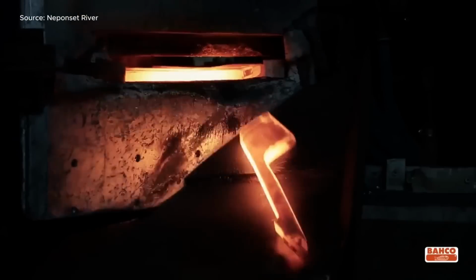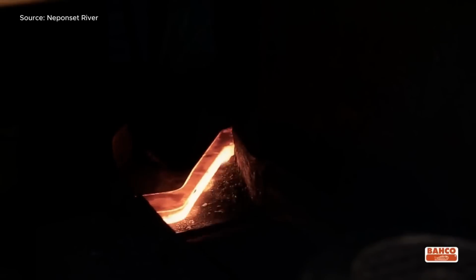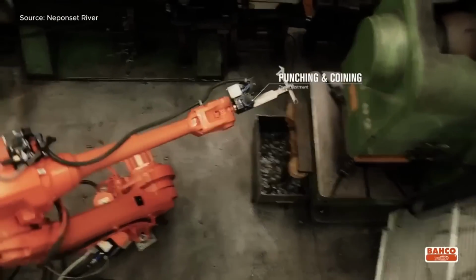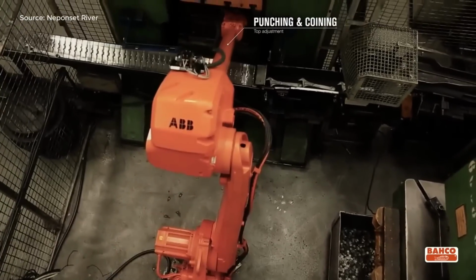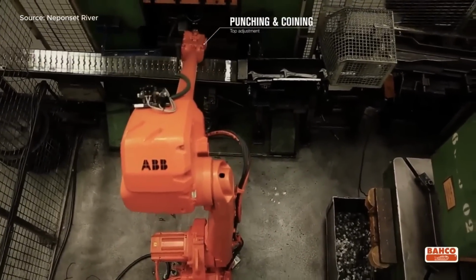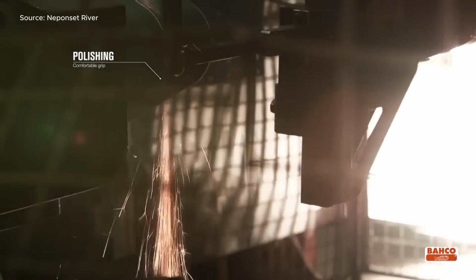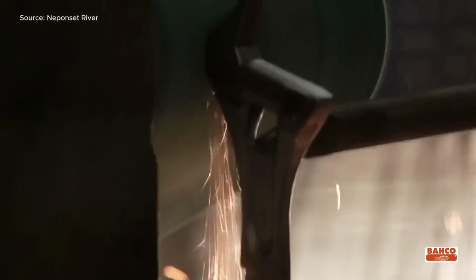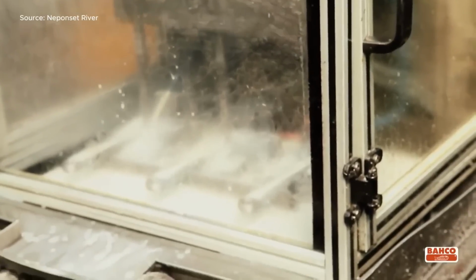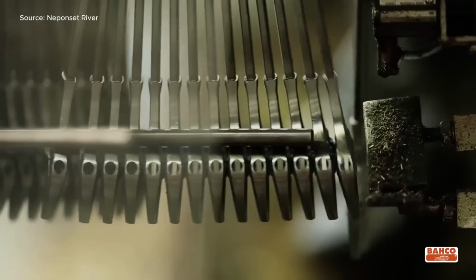The Bahco adjustable wrench manufacturing process begins with cutting using 1,000 to 1,600 tons of force. The blanks are then forged and hot trimmed at 1,150 degrees Celsius, ensuring strength and durability. Shot blasting cleans the surface before punching and coining shape the adjusting mechanism. Induction heating to 860 degrees Celsius is applied for hardening and tempering.